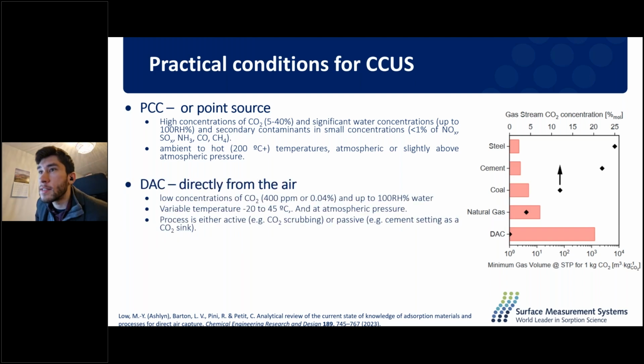Then, as Menjert mentioned, there's impetus to capture carbon directly from the air. This is called DAC, direct air capture. The challenge is the fact that CO2 in the air has a very, very low concentration. So 400 ppm corresponds to 0.04% by volume, about 3 or 4 orders of magnitude lower than in point source capture.